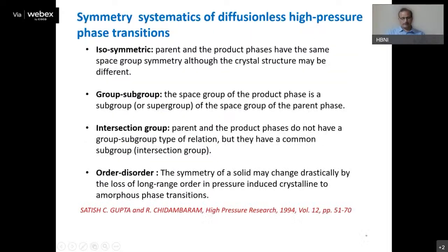Now I will come to the systematic classification that is given by Dr. Gupta and Chidambaram in this paper. We can broadly classify these high pressure phase transitions into 4 groups. One is the isosymmetric phase transition, where your initial phase and final phase have the same symmetry, and in many cases it is isostructural. It's entirely the same structure but with a different volume. There is a volume change. And then there can be a group-subgroup relationship, so the daughter phase has a symmetry that is a subgroup of the symmetry group of the initial phase.